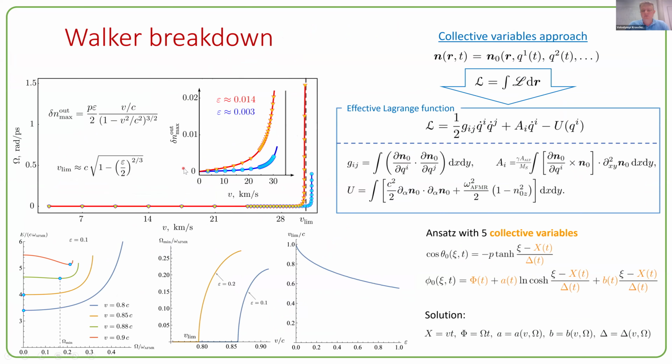So here we consider the domain wall motion in the direction when altermagnetic effects are maximal, meaning that this is the direction of these diagonals in which we have these altermagnetic bonds. If the direction is changed by 45 degrees, the effects will vanish. So yes, there is a strong anisotropy with respect to the motion of the domain wall. In another direction, its behavior looks like a usual antiferromagnet.